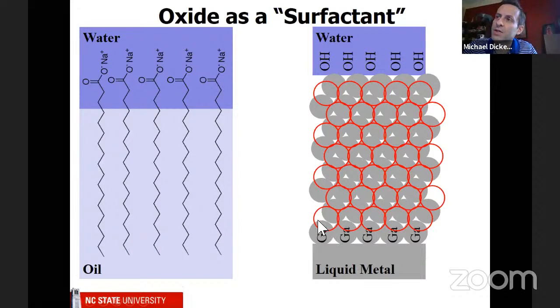So the oxide layer consists of gallium, and then these red circles are oxygen. And so gallium-oxygen bonds that terminate at this surface with OH. So if you think, like likes like, I don't know if you've heard that saying in chemistry, but the water should be happy at this interface. And then the last thing that's bonded down here is gallium. And so this interface should also be quite happy.